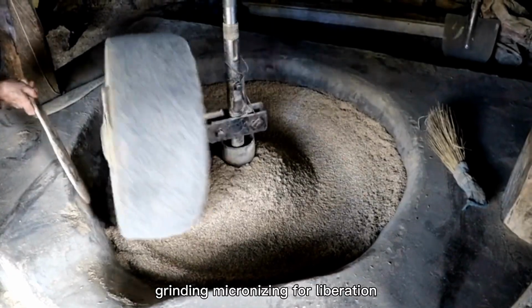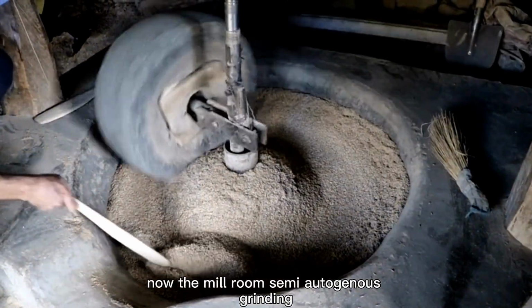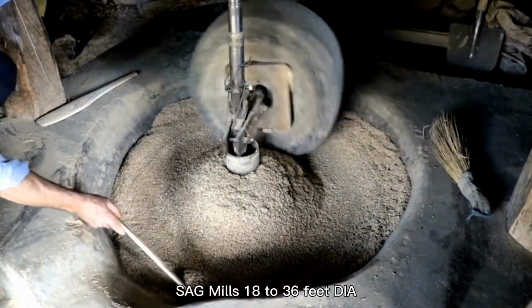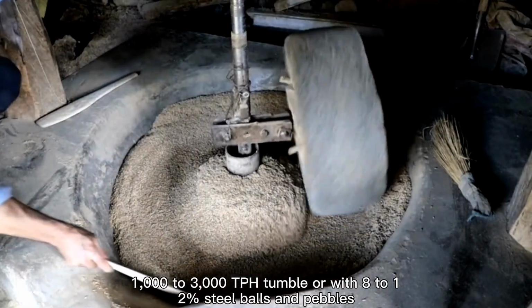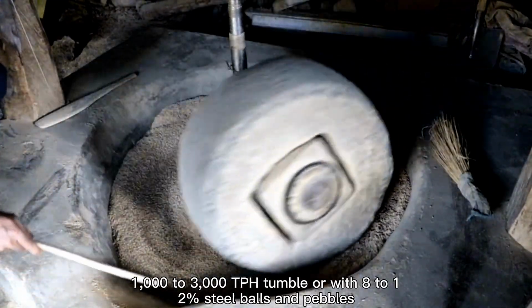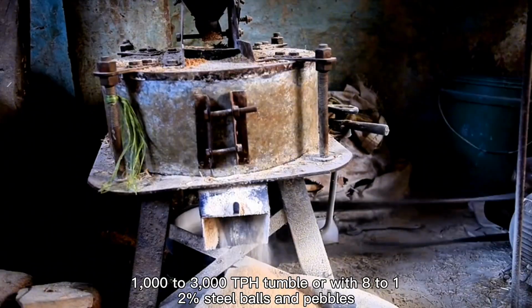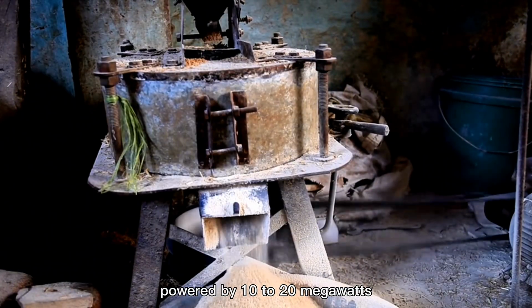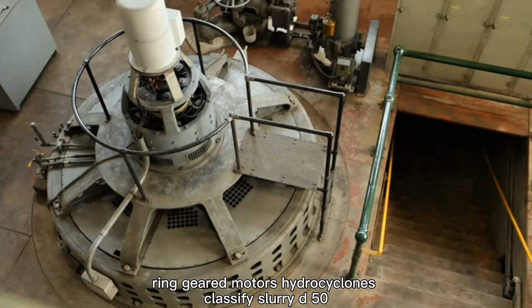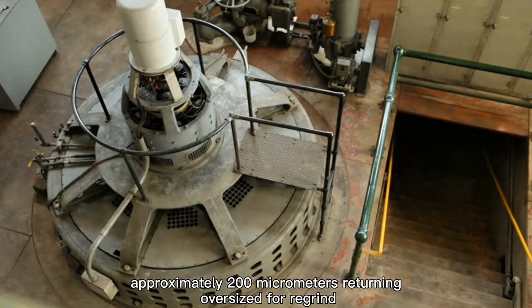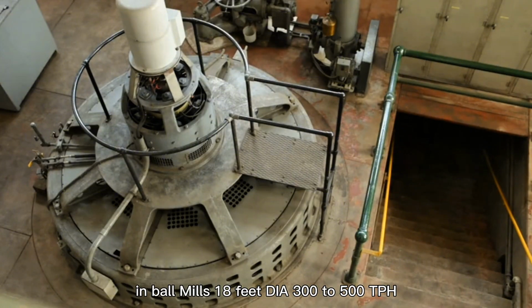Grinding, micronizing for liberation. Now the mill room. Semi-autogenous grinding, SAG mills 18 to 36 feet in diameter, 1,000 to 3,000 TPH, tumble ore with 8 to 12% steel balls and pebbles, powered by 10 to 20 megawatt ring-geared motors. Hydrocyclones classify slurry at D50 approximately 200 micrometers, returning oversize for regrind in ball mills 18 feet in diameter, 300 to 500 TPH. Fineness targets minus 100 mesh, 70 micrometers at 75 to 80%, for flotation.